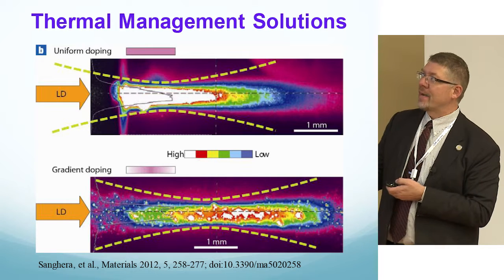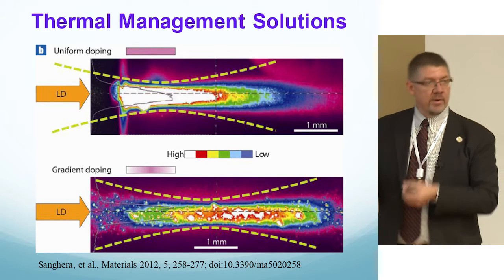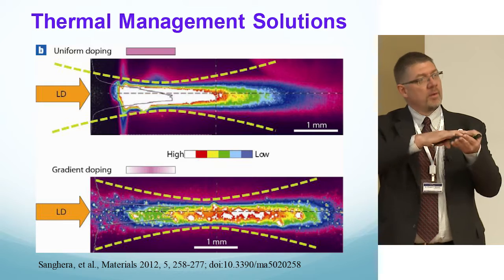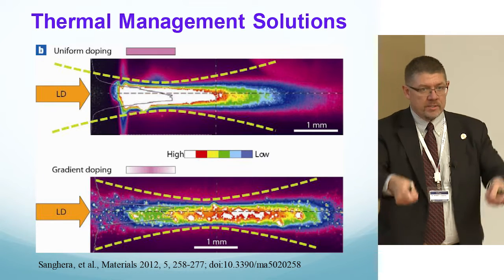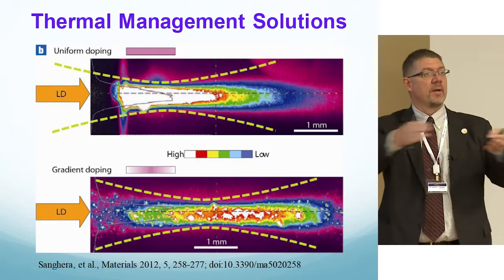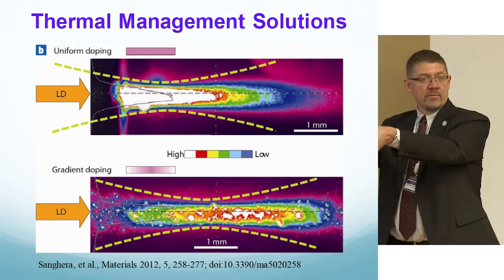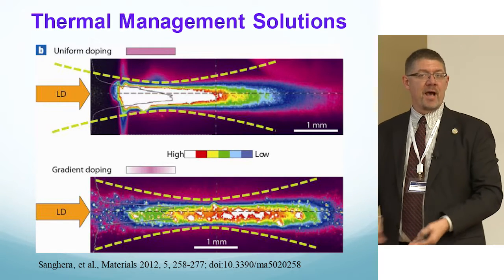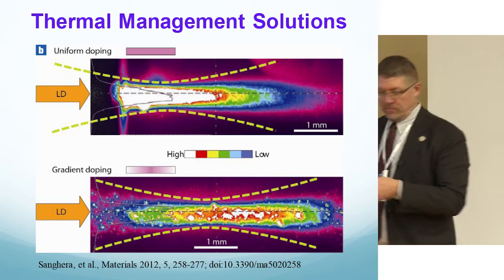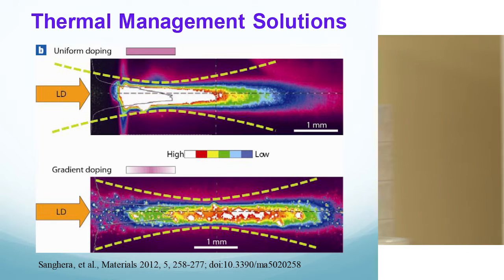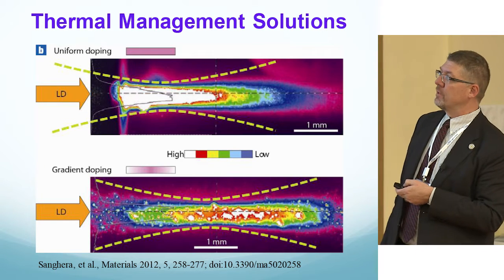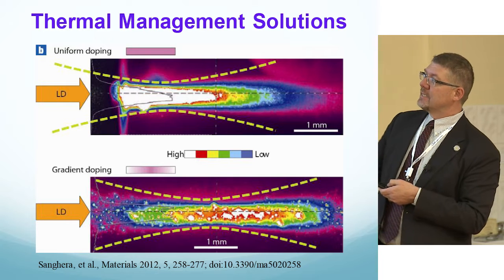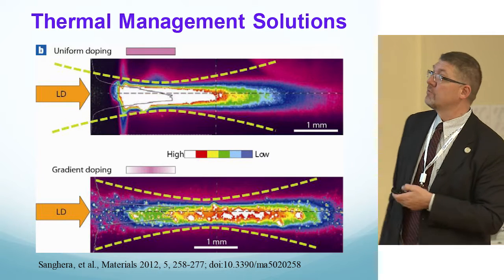And again, it all goes back to this tape casting. Making these very thin, wet tapes of material with one doping and then taking another one and setting it on top with a little bit higher doping, and higher, stack it up, put it in the furnace, heat it up, cool it down, take it out, and now you've got a gradient forced end to end. And then this is one that came out of Gary Messing's group with different dopants of erbium to try to stay away from the green upconversion process that takes place.